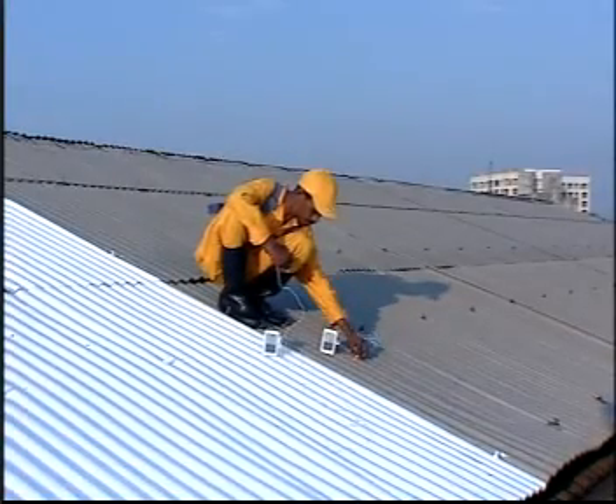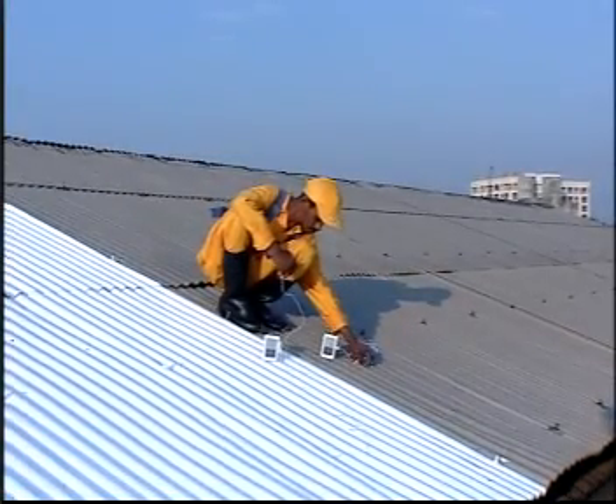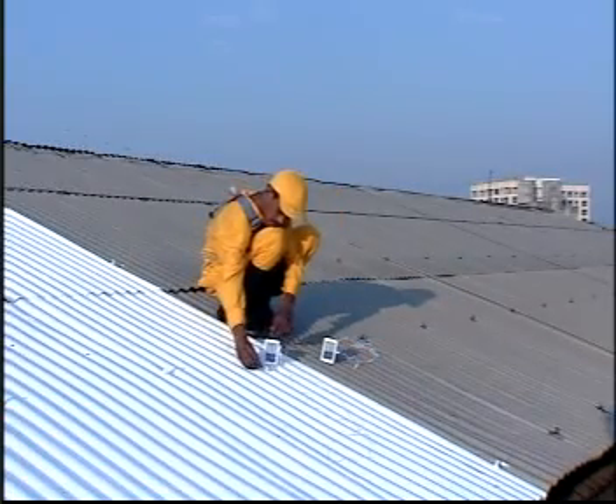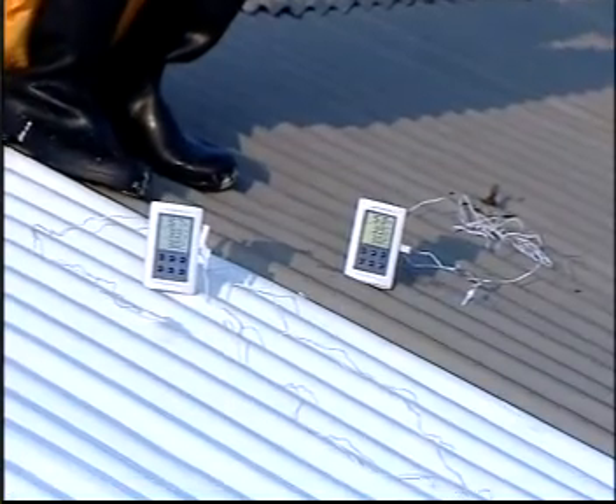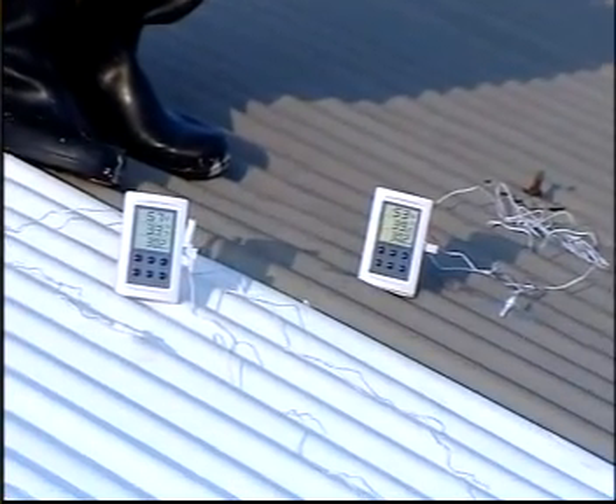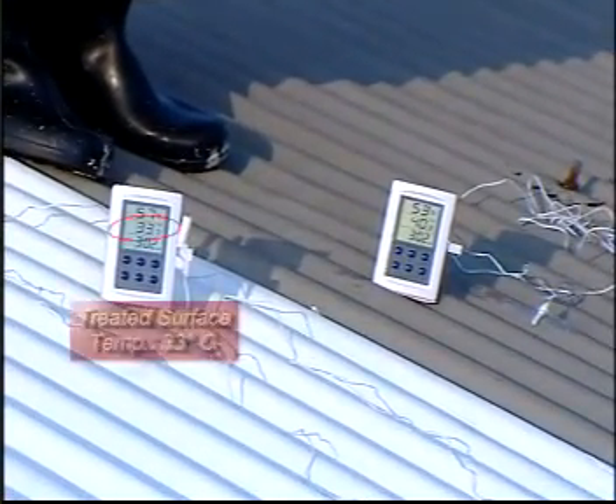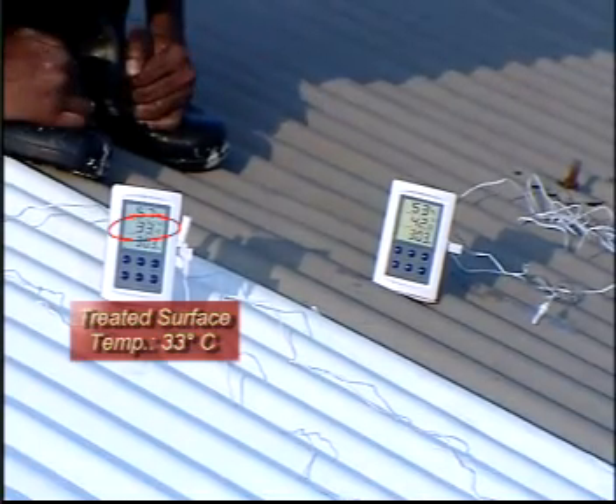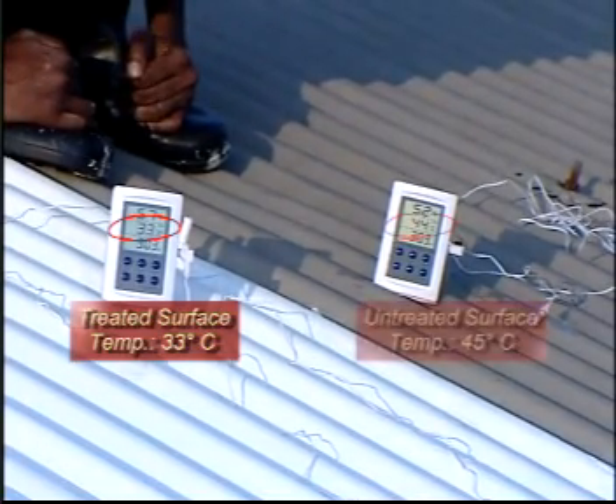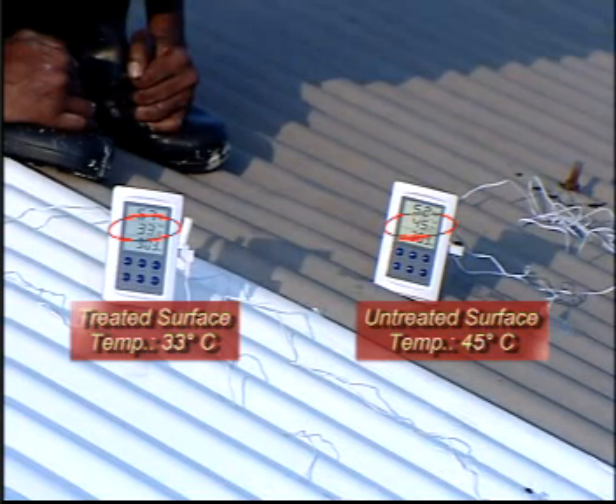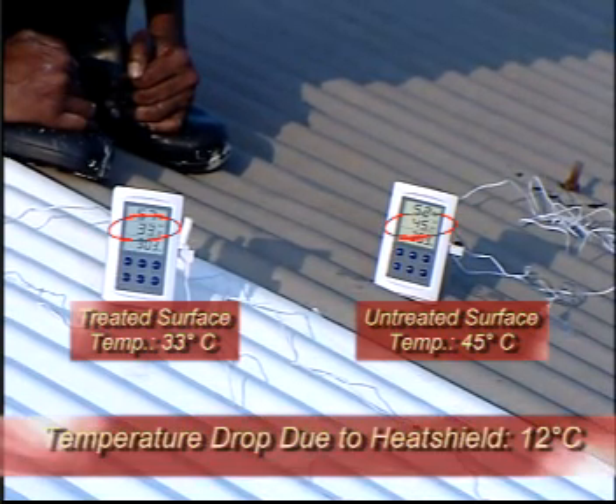The surface on the right is untreated. On the left side, we have applied 3 coats of Dr. Fixit Heat Shield. As you can see on the digital thermometers, the surface coated with Heat Shield has a surface temperature of only 33 degrees Celsius. But the temperature on the untreated surface is 45 degrees Celsius. Therefore, Heat Shield has resulted in a surface temperature drop of 12 degrees Celsius.